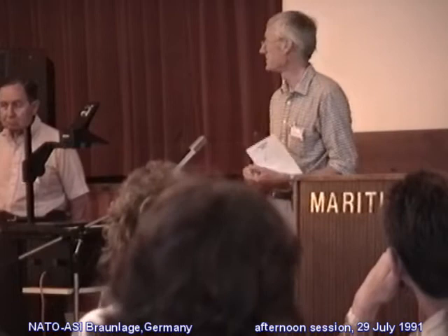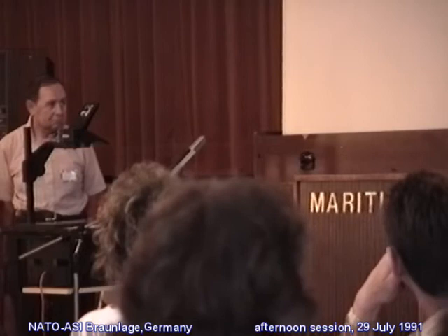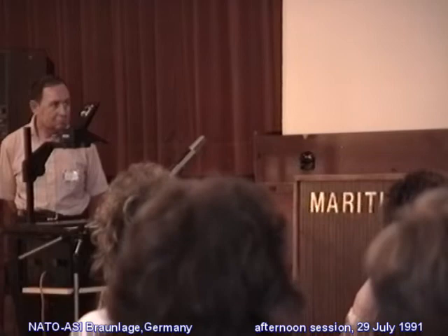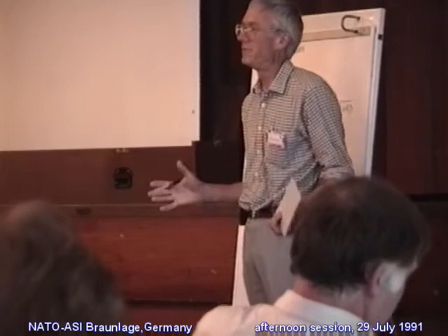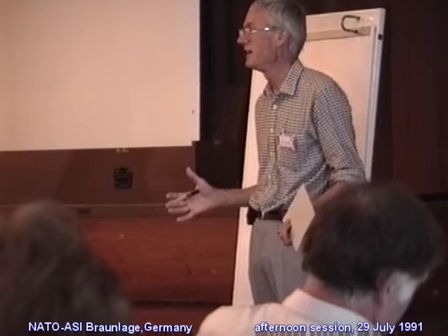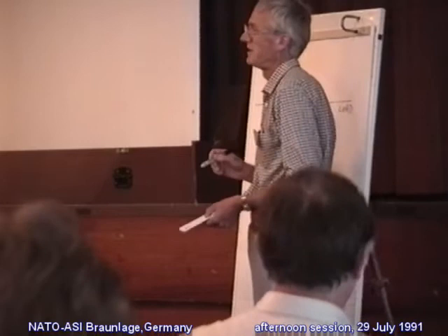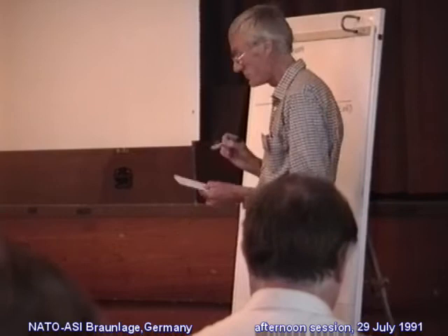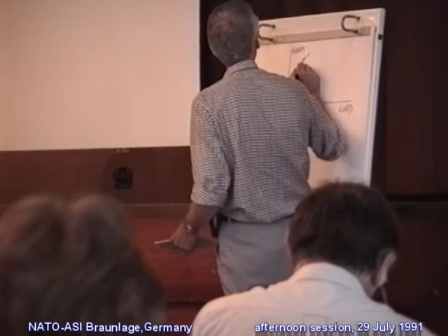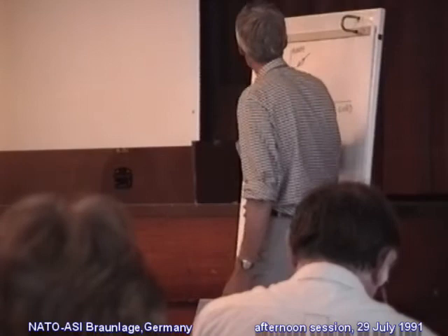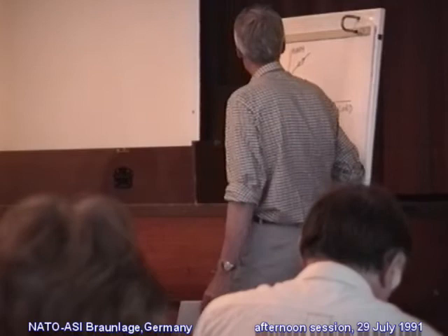And the other thing that comes to mind is the calculations that were done quite a long time ago by Professor Johnson and others. If we consider what happens for contact between a sphere and a flat, where he did take into account all the relevant energies, the surface energy, the elastic energy, and the potential energy. And I will be talking about this this evening, but for the moment, let me just say that, of course, there is irreversibility involved in that situation too. If you touch the surfaces together at zero load, they snap together and you get a finite contact area, and then if you increase or decrease the load, the area varies continuously with the load. You make the load negative, and eventually the area of course gets less, and then comes a point when the surfaces snap apart.